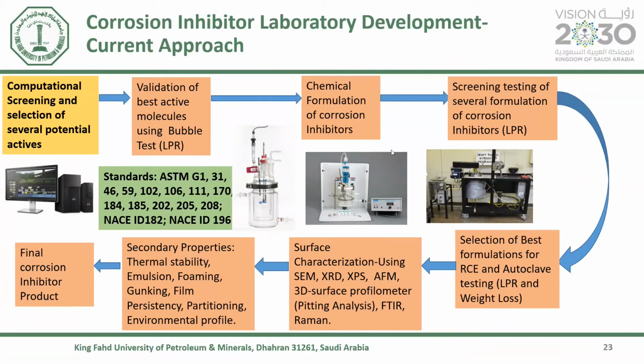From there, you go to chemical formulation, screening testing of the formulation, and selection of the best formulation using more aggressive conditions like autoclaves and maybe high shear conditions. Then you could do pitting analysis and secondary property testing, and you still go to your final corrosion inhibitor product. But here, mind you, you will still use a lot of standards. So although it is capital intensive too, it gives you a faster approach to select your active ingredient.